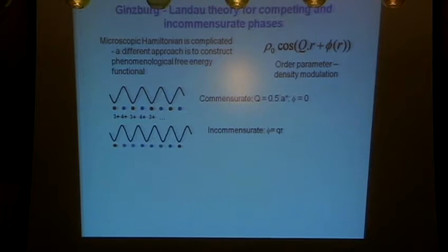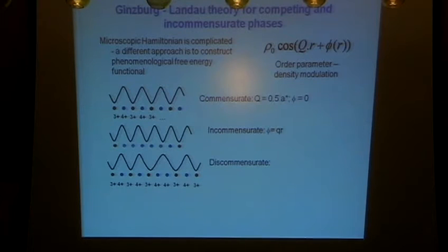If I had an incommensurate wave which was just uniformly stretched, then of course the valence will be changing smoothly over here. This will be sitting up and down. And I would get that by choosing the same Q here, but having this phase grow linearly with position. And so the actual wave vector here is big Q plus little q. And I can, of course, do something in between, which is to make something which has so-called discommensurations in it, to have the same average period as this, but to make it by having it locally locked, make a mistake, locally locked, make a mistake. And you can see that kind of thing has a stripe, a sort of an extra 4 plus.